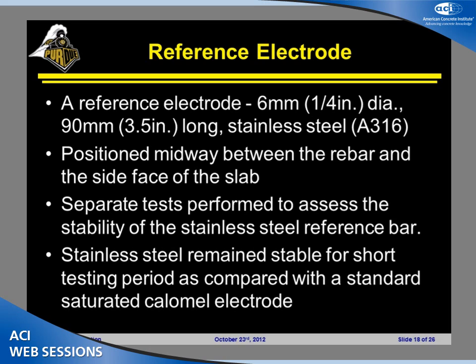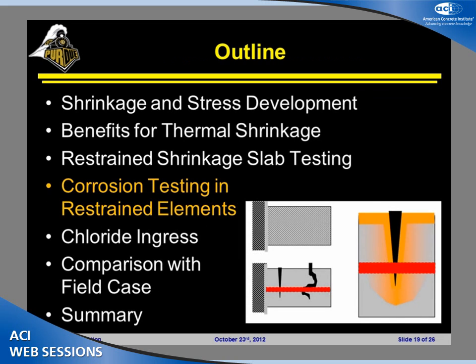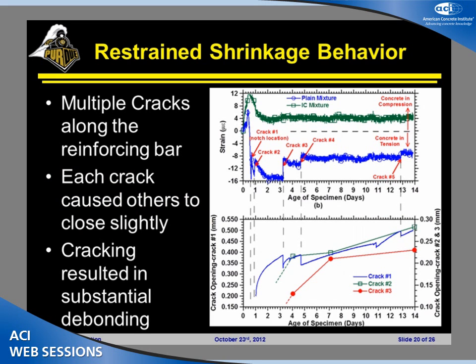Again, we're going to be doing corrosion monitoring in here, so we're going to be using a reference electrode. We're using a stainless steel reference electrode that for the duration of this test has remained relatively stable. And what we're going to do here is talk a little bit more about some of the results.